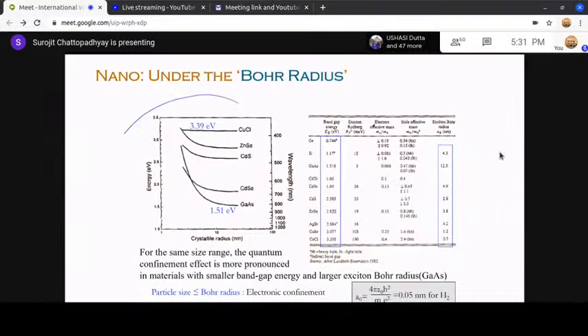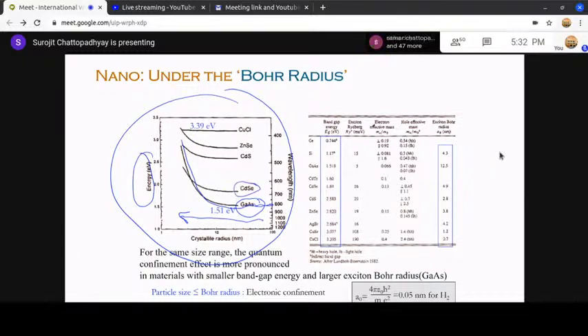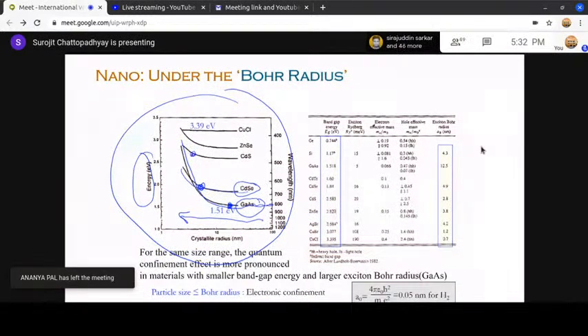So in this plot on the left, we have plotted the absorption energy as a function of crystal size in nanometers for different materials. You have gallium arsenide, and as the gallium arsenide crystal becomes smaller, this absorption energy stays the same and then suddenly increases. This behavior is the same for all. Cadmium selenide also increases somewhere over here. For cadmium sulfide, the change in the energy happens somewhere over here, and so on. So now the question is, what is happening at these points?